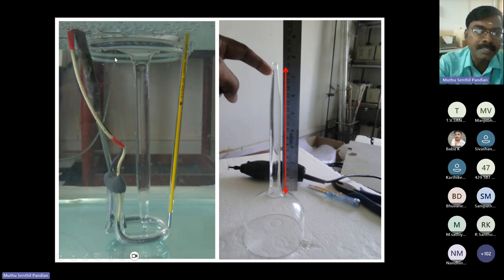As I mentioned, we have to maintain a uniform temperature at the top and bottom portions. Normally, we maintain the temperature at the top portion like 38, 39 and 40 degrees Celsius. So we have to reduce it by 0.1 degrees Celsius per day or 0.01 degrees Celsius per hour. Similarly, we have to maintain this for the whole crystal growth run, and we have to wait until it reaches room temperature. Once it reaches room temperature, we have to take it out from this water bath.